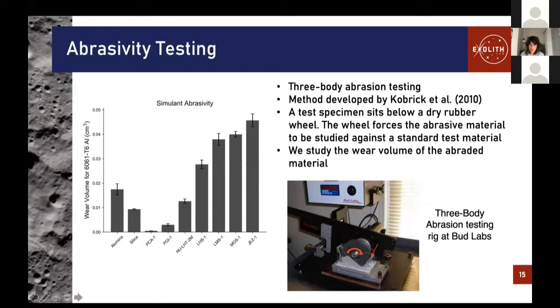The idea is that, so this is what the test rig looks like, you have this rubber wheel, and you load simulant against the wheel, and then below that there is some standard test material, and the wheel is going to spin and force the test material against the surface that's going to be abraded, at a known angular velocity and for a known amount of time. And then you study how much volume is worn away from that material that you've abraded.